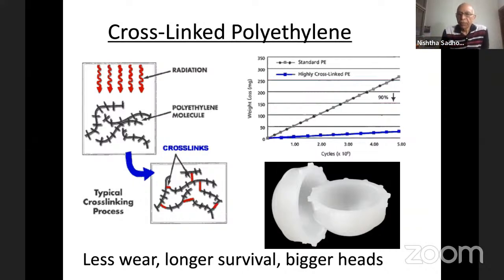the wear being much less, one can use a relatively thinner shell, thereby increasing the head size, which in turn would reflect on the dislocation rate. The general dictum is the bigger the head, the less the chance of a dislocation. However, this is just one of the factors. It must not be taken as the sole criterion, because there are many other factors at play. But this definitely is one of the strong endorsements of a highly cross-linked polyethylene use.